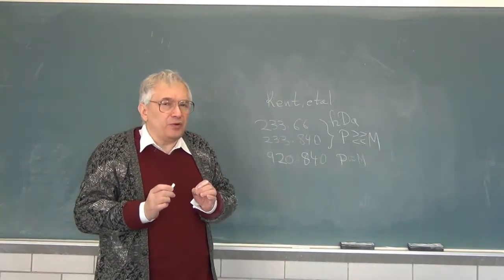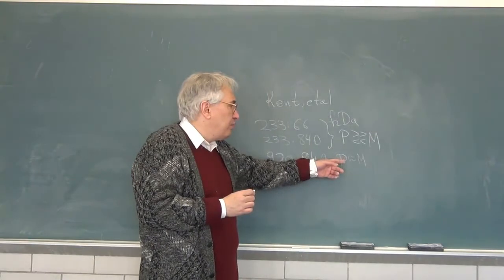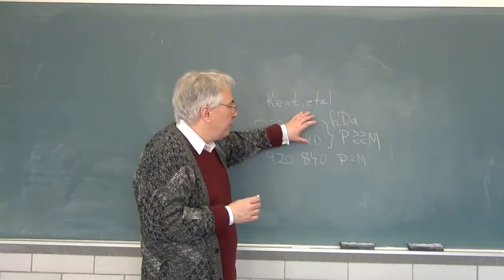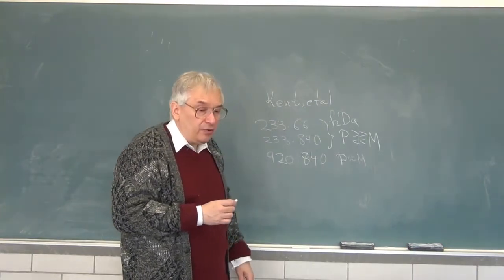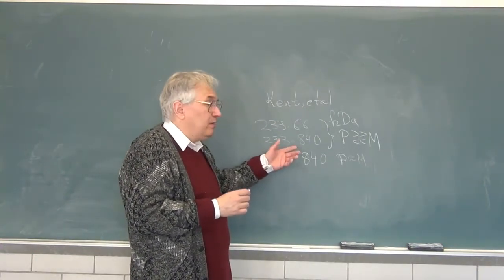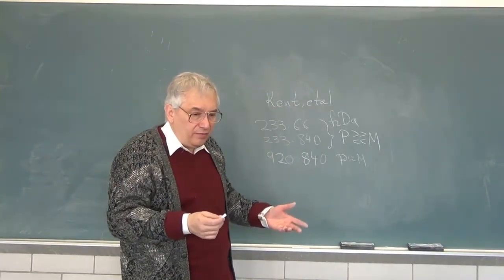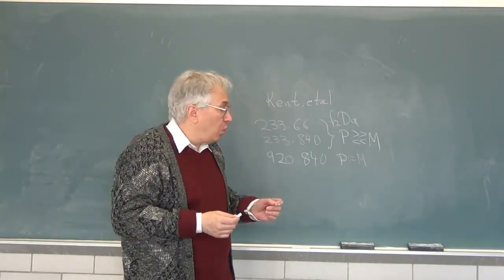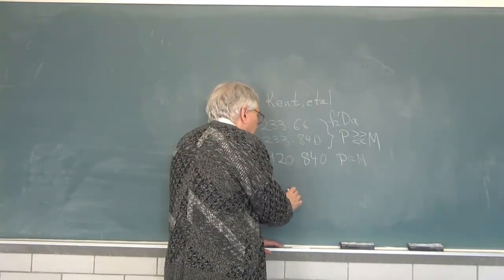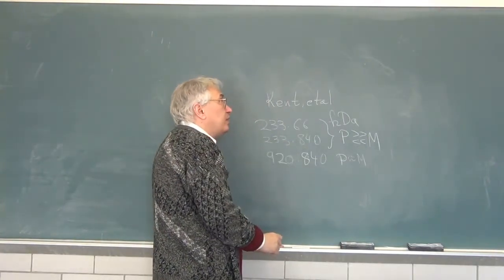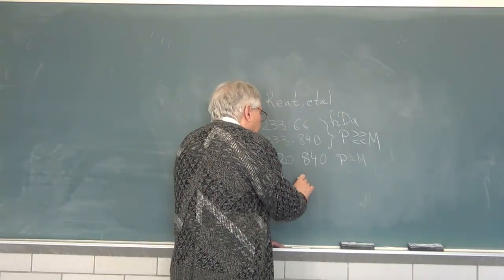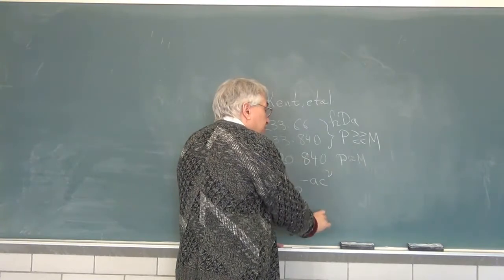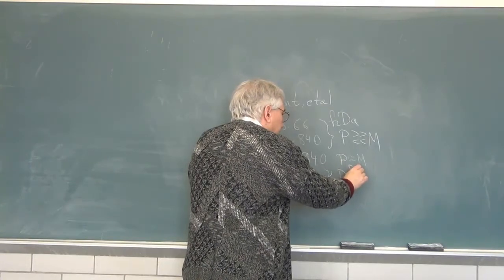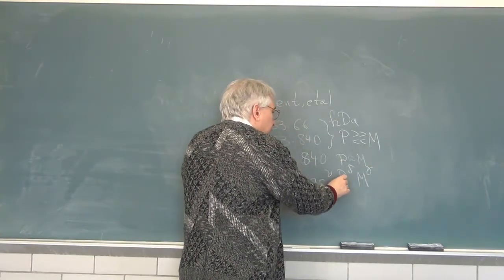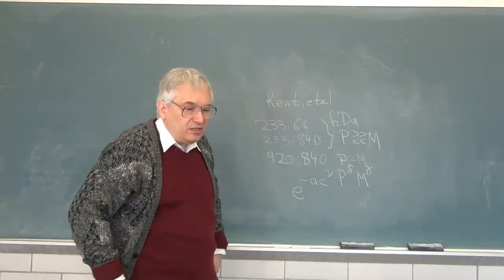There are models that predict that you see one behavior for P about equal to M, and very different behaviors if P and M are very different. Well, maybe you do get this behavior if they're different enough, and we'll get to that a bit more in a moment. The important issue here, though, is there are three curves corresponding to these three combinations of materials, and the three curves are accurately described as there's concentration dependence, and there is a P to the delta and an M to the gamma. There is a matrix and probe molecular weight dependence.